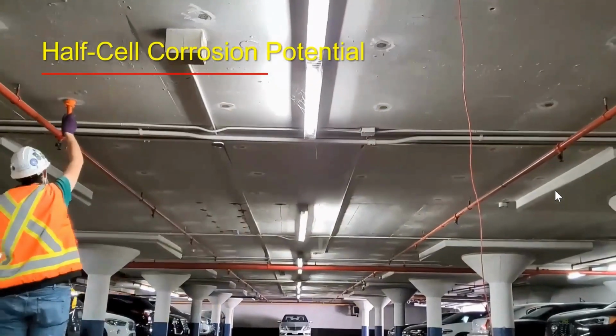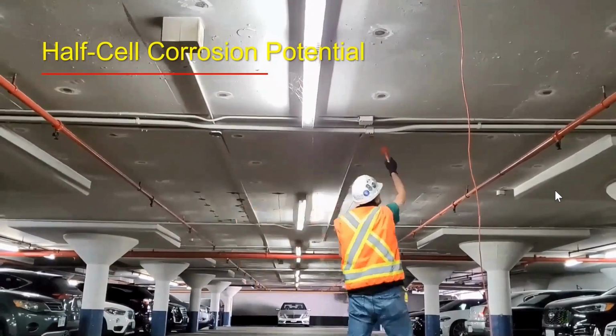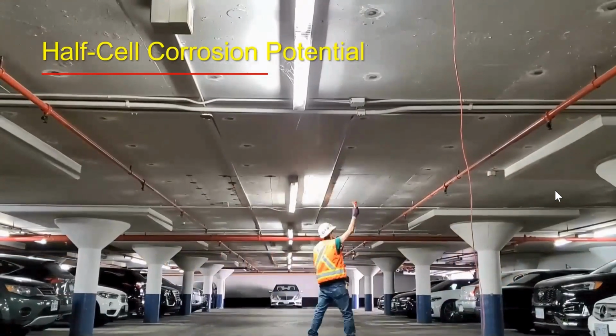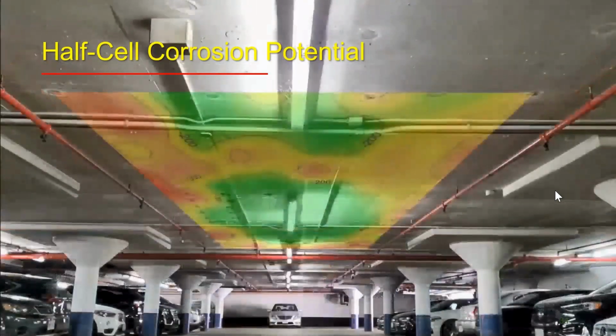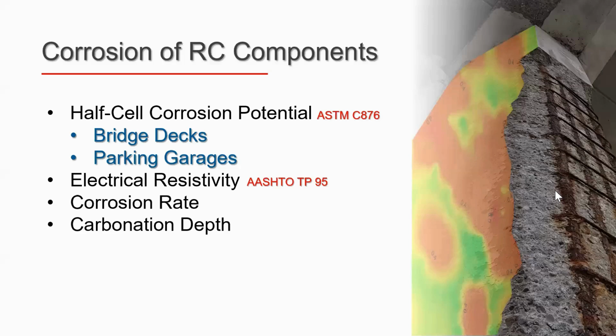You normally take a reference connection to steel reinforcement, and then you perform the testing on several points in a concrete slab. The results can be presented as a contour plot, often used as half-cell corrosion potential map, and this map can be interpreted: when the results are more positive than minus 200 millivolt for copper-copper sulfate electrode, then the chances of active corrosion is less than 10%. And if it is more negative than minus 350, then the chances of having active corrosion, like the red zones, is more than 90%. The test remains uncertain for the range between the two. So you have to always handle the test results with extreme care.